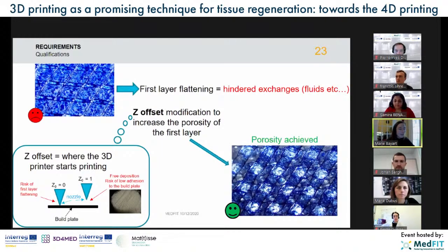Here we see that we have first layer flattening, because we didn't choose the Z offset right. The Z offset is where the 3D printer starts printing. If we choose a low Z offset, the nozzle will start printing very close to the build plate and it will flatten the first layer. And if we choose a too high Z offset, we will begin to print very far away from the build plate, and we will have low adhesion to the build plate. So we tried different Z offsets to avoid flattening, because flattening means that there is no porosity on the first layer, and it hinders exchanges of fluids and nutrients. And then we had a very nice porosity with the good Z offsets, and so nice exchanges.